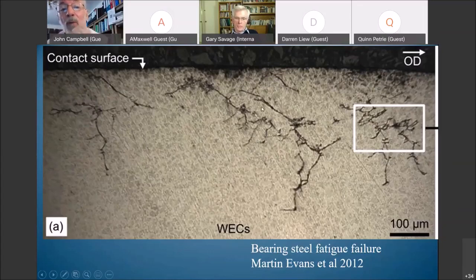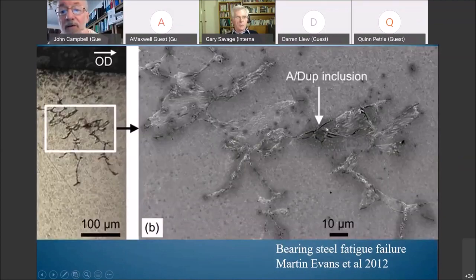And what happens now is that, I don't know whether you can see this, but we have a small area here where there's just something going on right in the center there. And if we look at our next slide, here is the next slide. And in the center there is an inclusion. Now, it's not very clear on here, but there are little kind of wings either side of this inclusion. And there's various white etching cracks. So there is an event going on here, taking place, which is a real fatigue event.